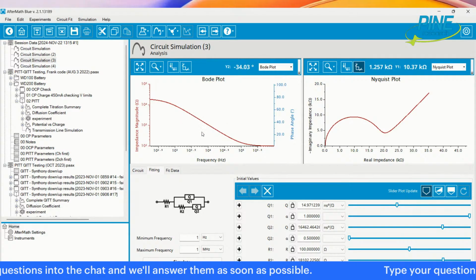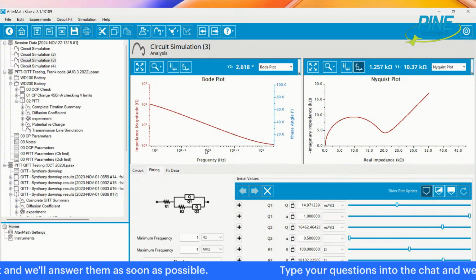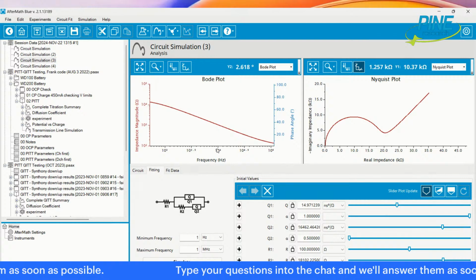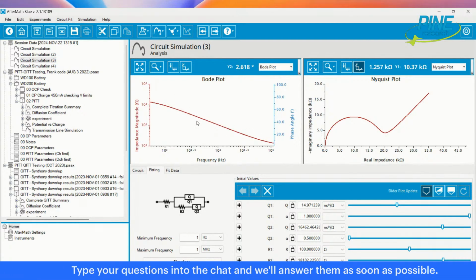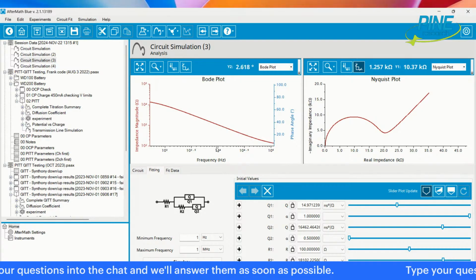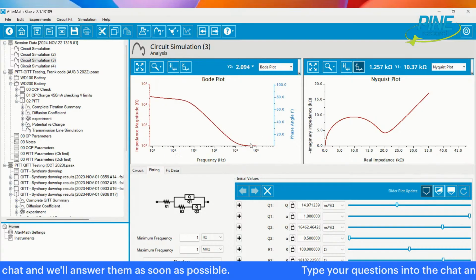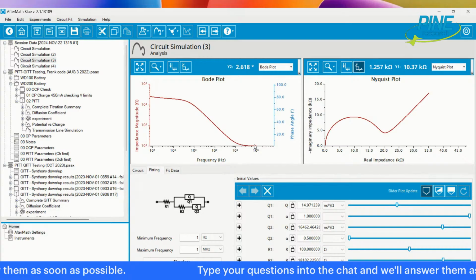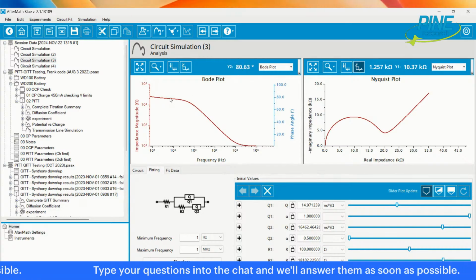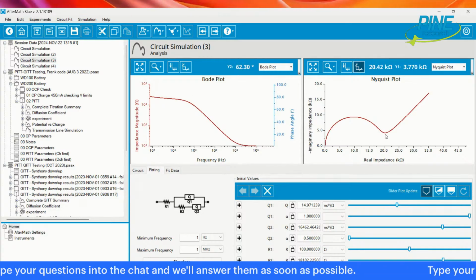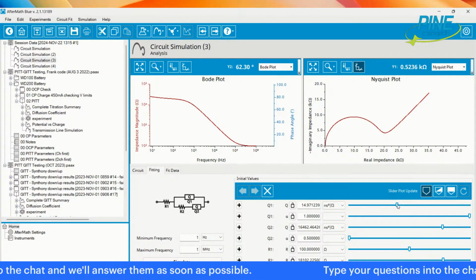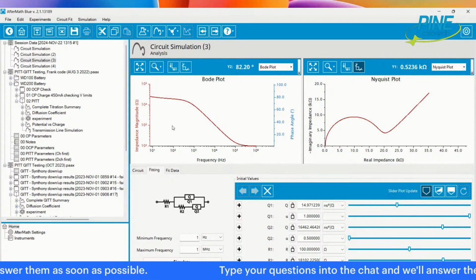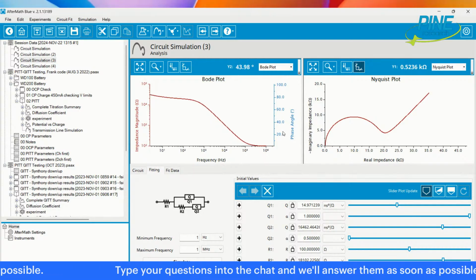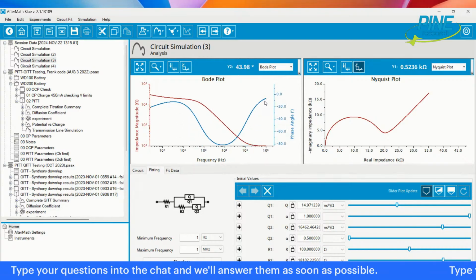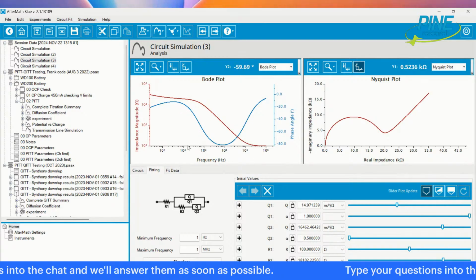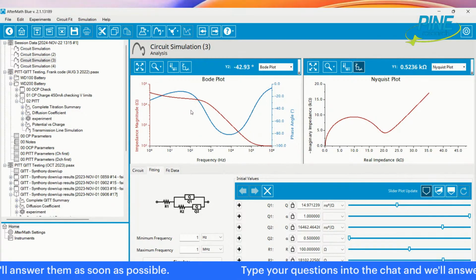A pure capacitor looks just like this. It has just a straight line. So a portion of your impedance magnitude that's a straight line correlates with mostly capacitive behavior. Plateaus correlate with mostly resistive behavior. There's a plateau at the beginning here, and a plateau at the end. That correlates to the start and the end of this semicircle. That's the minimum of the phase angles, where the phase angle is closest to zero. It's mostly resistive. And then the other part, the Warburg element, does weird stuff.